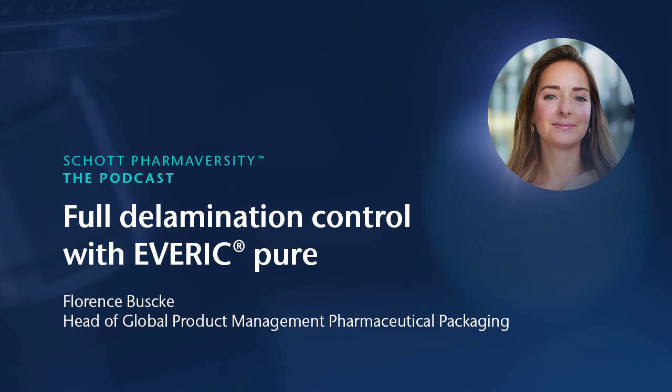So for this predictive testing to help in going towards 100%, at SCHOTT we have assembled a test kit. On the one hand we have so-called DELA test vials. That is vials that fulfill the hydrolytic resistance requirements according to the norms. But on the other hand, they fail what we internally call the quick test, which is a test to check if additionally a threshold is maintained that is well known for our production to have vials that are not prone to delamination.